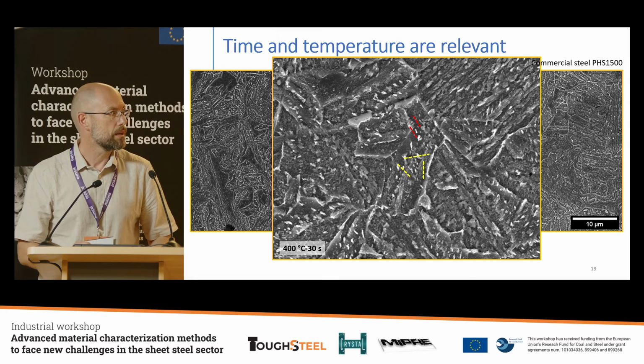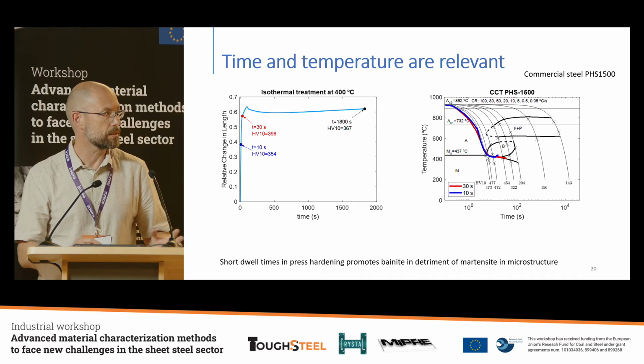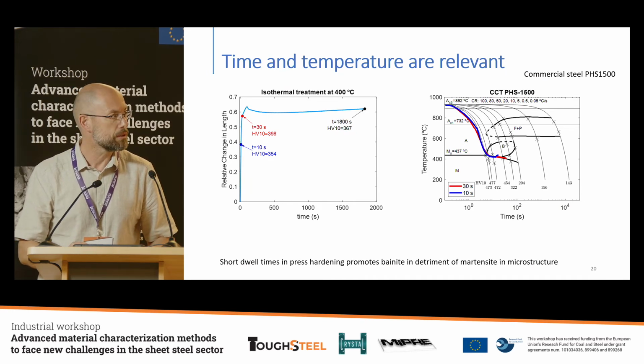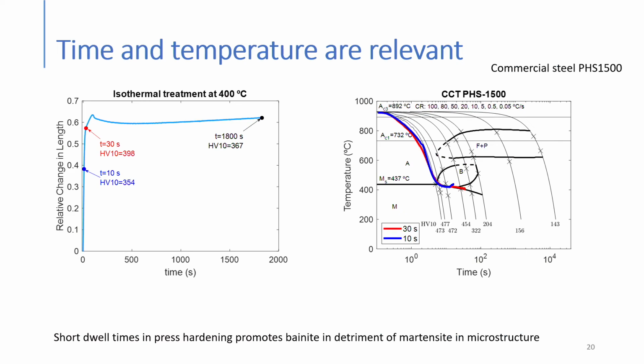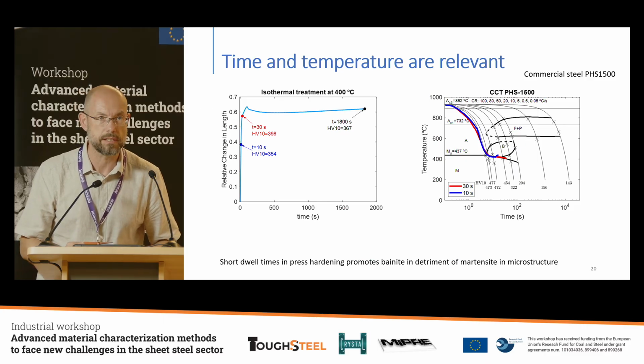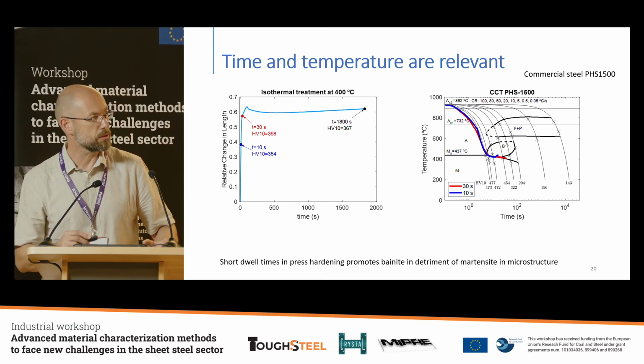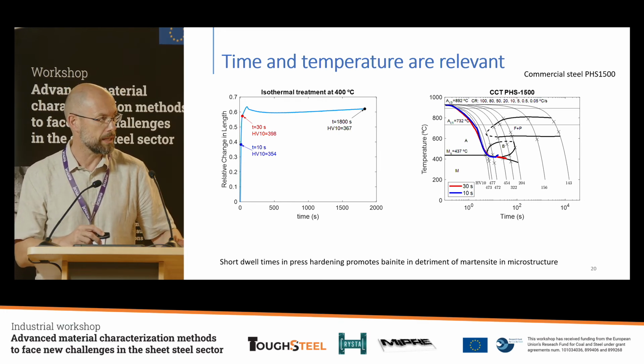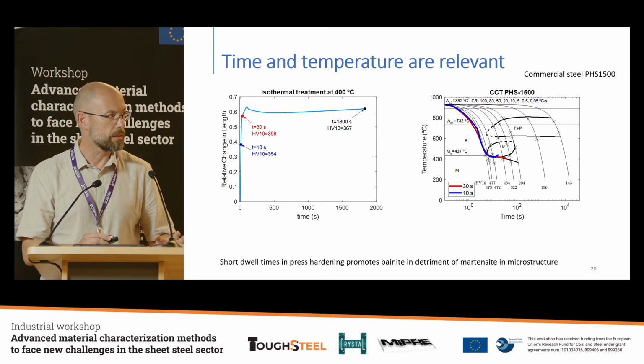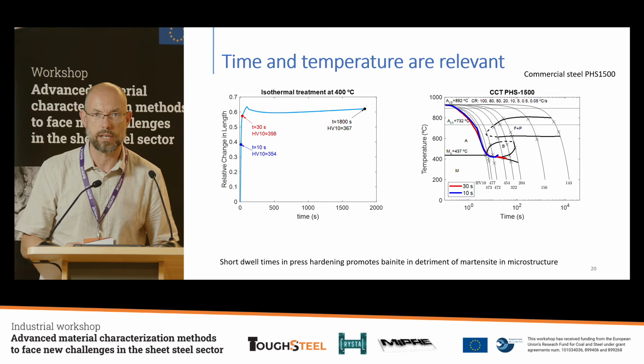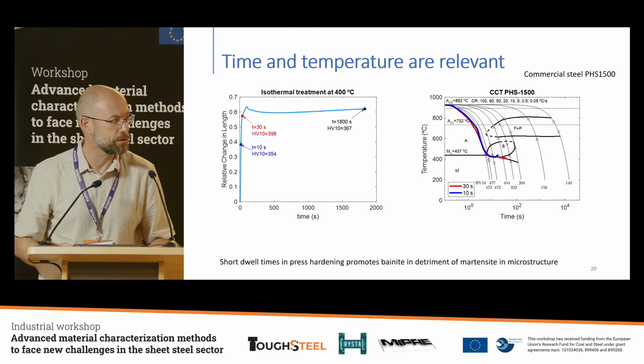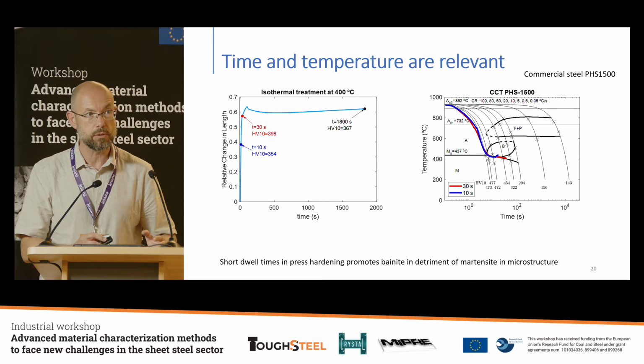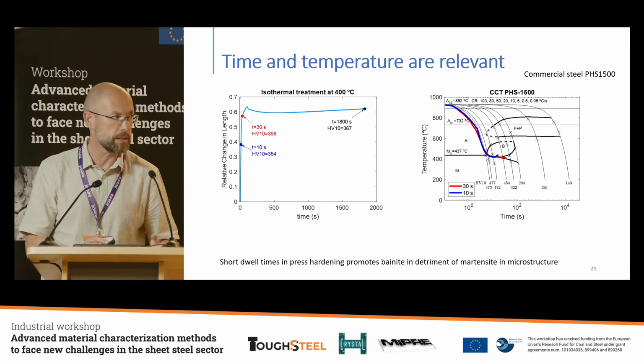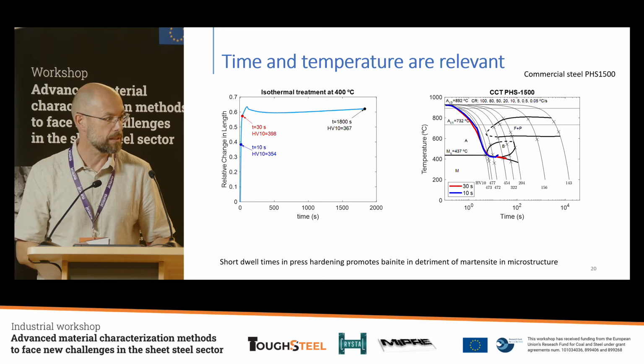And then combining both, as Jaume mentioned before, when you are cooling or processing your material and you have the PHS 1500 CCT, you are exactly moving in this area, where you have bainite and you have martensite. So depending on the time that you stay during the processing, you will have more bainite or more martensite. This could be at the beginning a disadvantage because you are not able to reproduce exactly the same microstructure, but if you are able to control that, then you will control the properties. The process is just controlling the closing time during the press hardening.